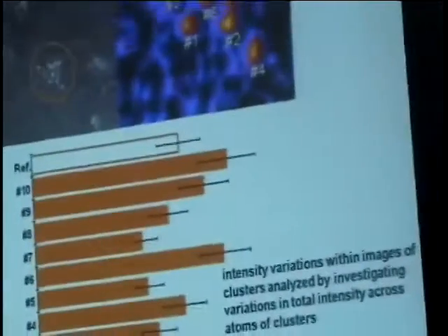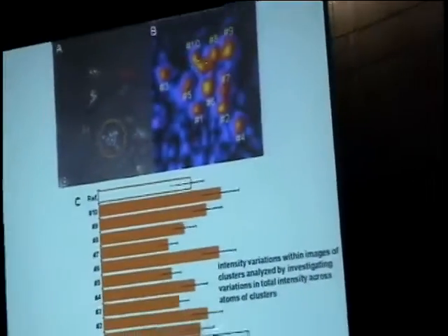And so consistently finding evidence of the number of atoms in each of the clusters. In one of these, you see a smear, and what that's telling you is we're at the edge, because there's been substantial motion of one of those osmiums under the influence of the electron beam. So we're at the edge in terms of what we can resolve structurally with the microscopy.